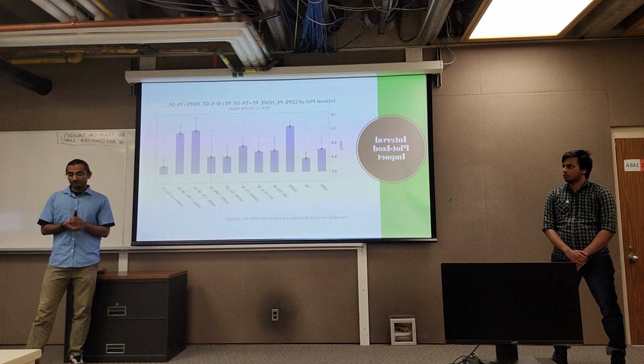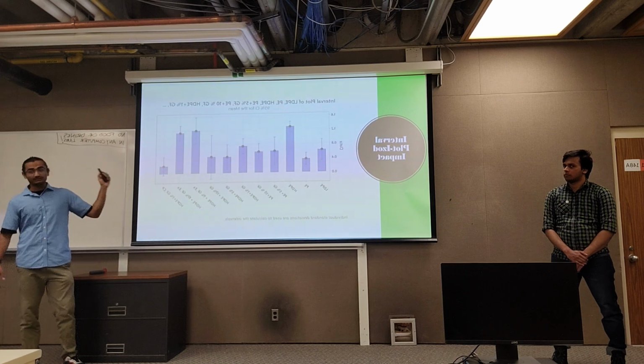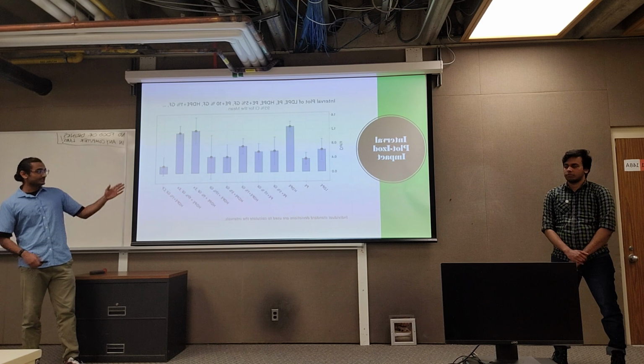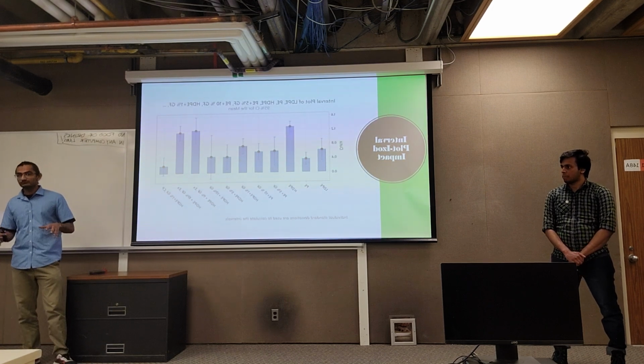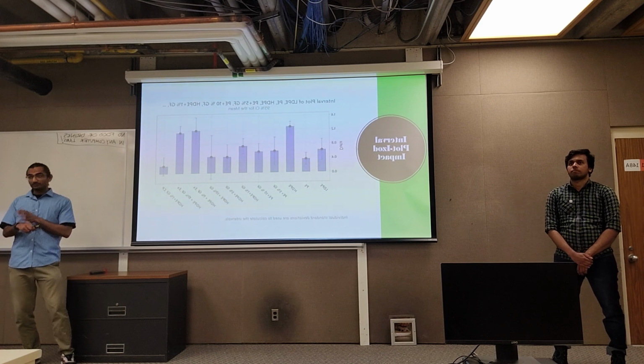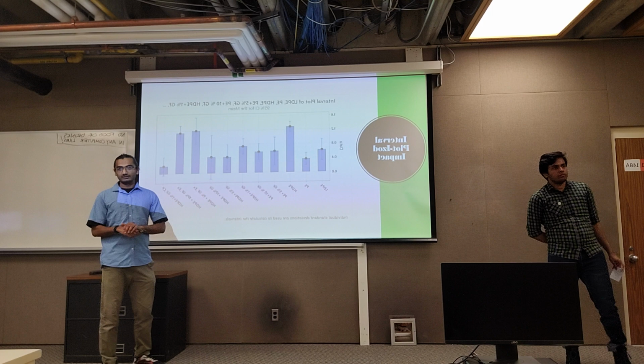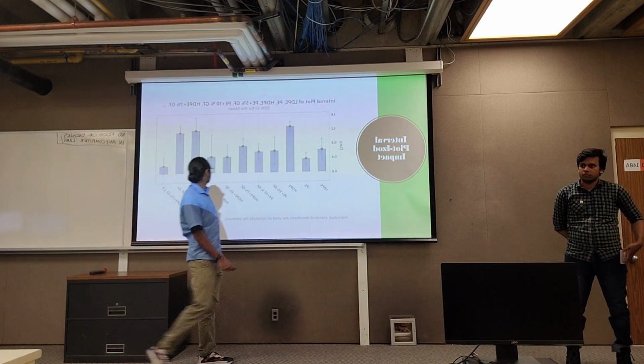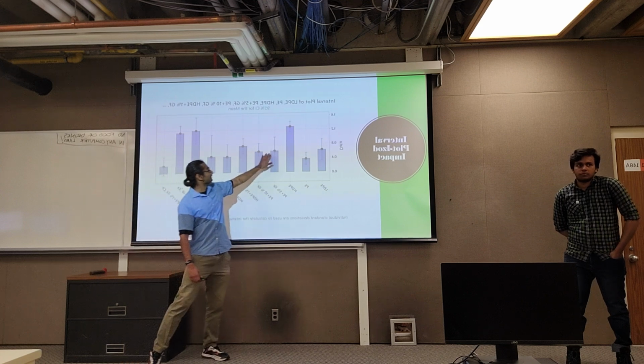The trend was reversed when we went with the virgin PE. So in the case of PE, with the addition of reinforcement through the process of compression molding, there was an increase in the impact values. As you can see, from here to here, there is an increase in the impact strength results.